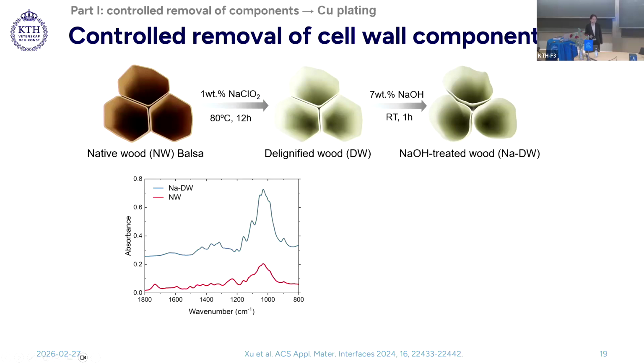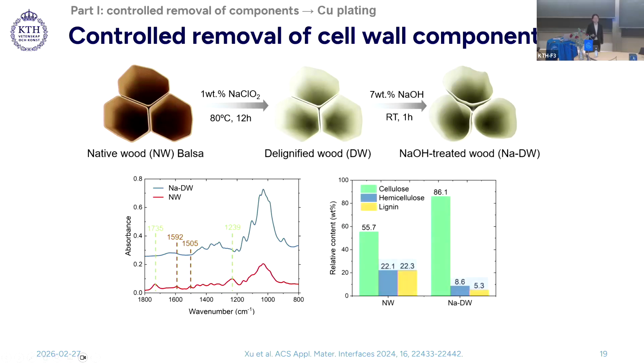From FTIR spectrum, we can see the absence of aromatic skeletal vibrations, as well as the characteristic bands of hemicellulose. Carbohydrate analysis also reveals a sharp decline in lignin content from 22 to 5%, and hemicellulose content from 22 to 8%, indicating the partial removal of lignin and hemicellulose in the engineered wood template.